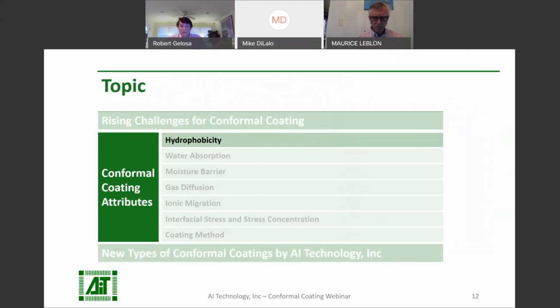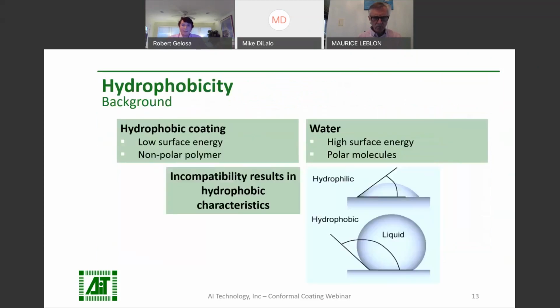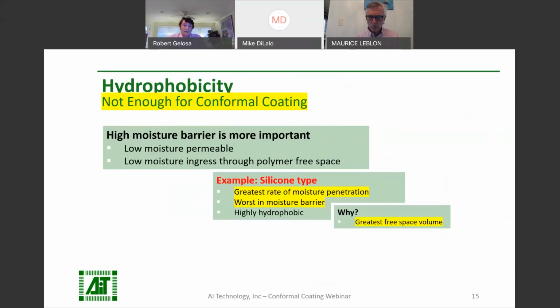First, let's look at hydrophobicity. So hydrophobicity is definitely a desirable property in conformal coating. We want water to just roll off. Have you ever done a water drop test? Just put a drop of water on a surface. If the surface is hydrophobic, we'll see it ball up. But if it's hydrophilic, we'll see it spread. So hydrophobic coatings repel water, and they may even be suitable for short-term water immersion. But many users of conformal coating mistakenly conflate hydrophobicity with total coating protective performance. On its own, hydrophobicity is not enough.